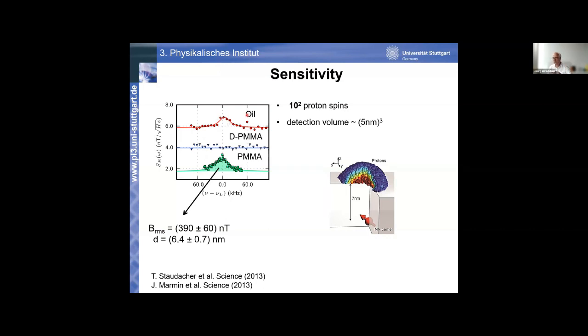This can be water, it can be oil, which is not evaporating that fast. Technically it's a bit easier, but it's just a proton, hydrogen-containing liquid. You can do this also with a solid. PMMA is polymethyl methacrylate, a polymer which also contains protons. You see the same type of signal, but you can deuterate that specimen, and then the signal disappears. So that gives you pretty good confidence that you really see a proton Larmor precession modulated magnetic field.